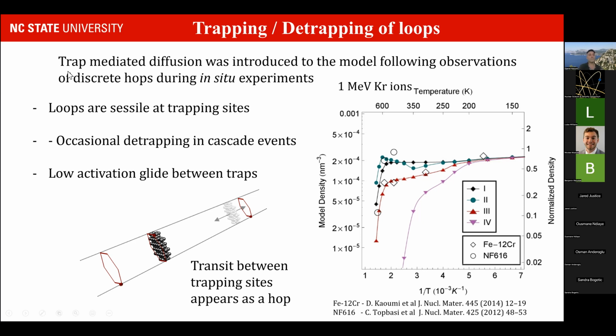And Aaron and Brian came up with this trap-mediated diffusion process. They actually introduced it into the model to take into account the discrete hops that we saw during the in situ experiment. And the idea is basically that your defect is trapped at a given position because of impurity or because of a defect around. And occasionally, if let's say a point defect cascade happened nearby, you can have a shock wave that is produced and will allow this loop to free itself from the trapping site. And then at that point, it's going to glide extremely fast in the gliding direction determined by your crystal structure. And this is why we see this type of 1D motion until it's trapped in another position.